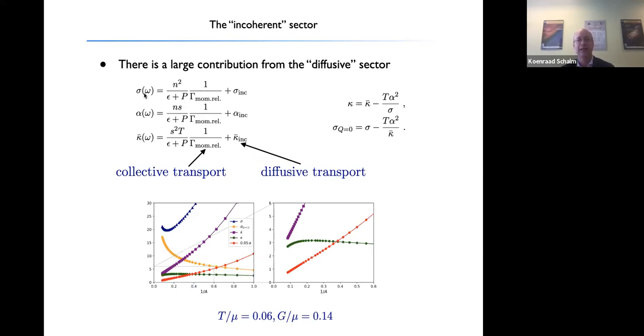Here you see it explained in formulas. There's this inverse momentum relaxation rate part, but as A increases, this rate goes up, this becomes larger and larger, and so this term becomes smaller and smaller, and it becomes more and more dominated by this incoherent part.